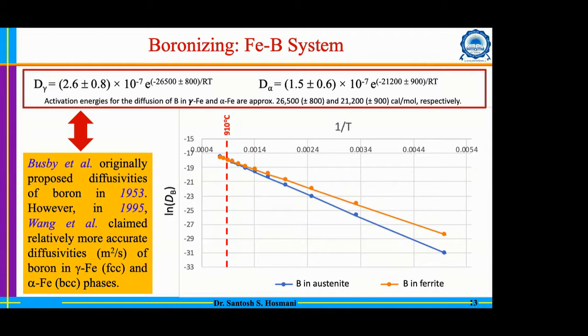The only criterion is that high temperature actually helps us to have effective chemical reactions happening at the surface, because chemical reactions also have their own activation energy barrier. So high temperature will definitely help us to overcome that barrier, and your chemical reaction rate will be faster. That advantage you will get due to the high temperature along with the high diffusivity.